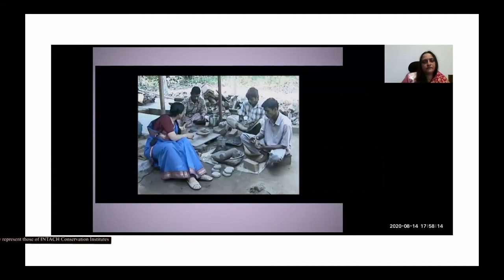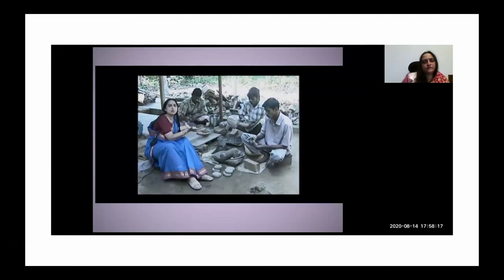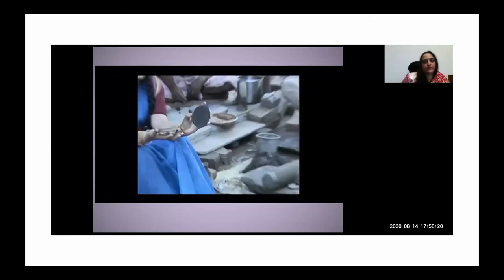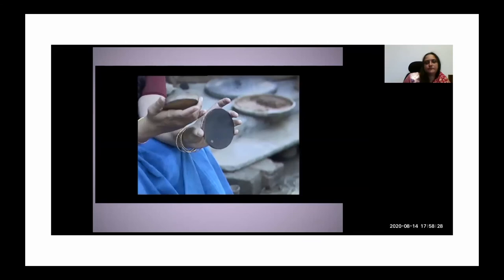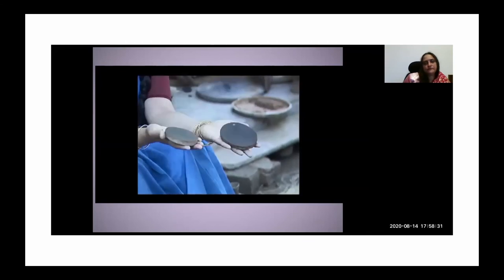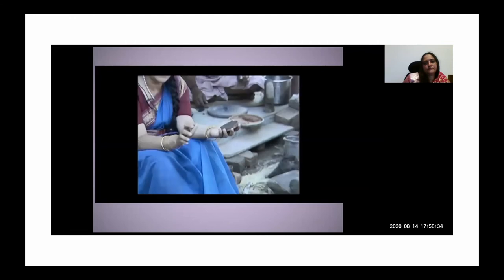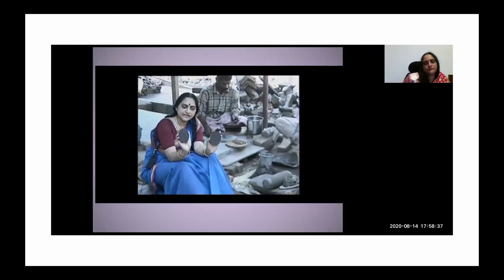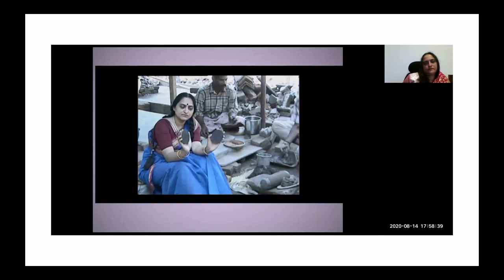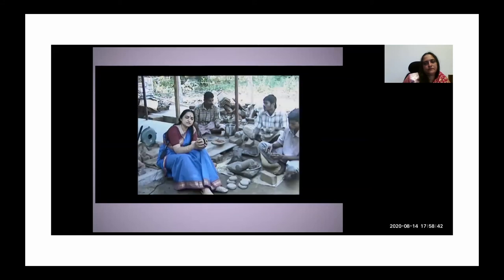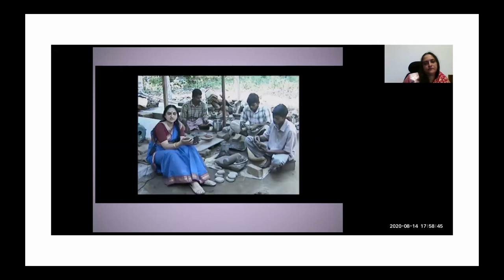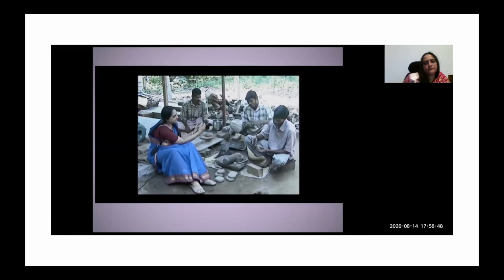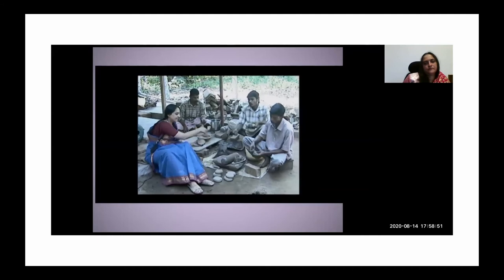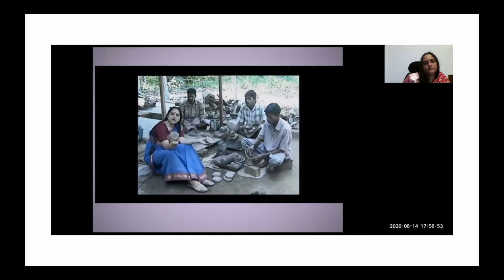These are two disc molds. These are rough clay disc molds, then they apply a very fine clay layer made of ground pottery on it so that it gives a finer finish, and then finally he applies a layer of charcoal so that you get the finest surface possible against which the mirror blank is cast. Then these two disc molds will be placed together, and tiny pieces of spacers are kept to maintain the hollow between the disc molds. And then it is encased in clay.